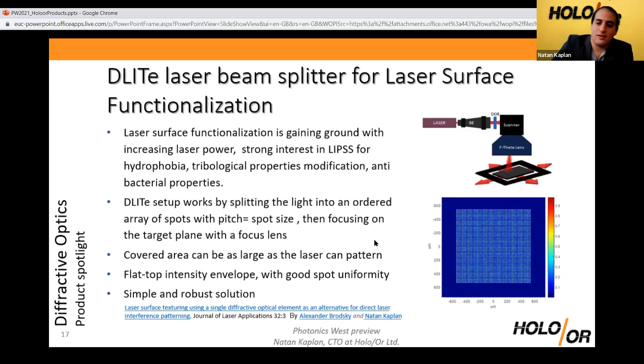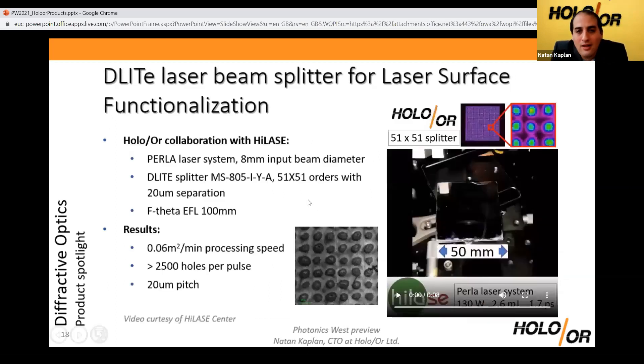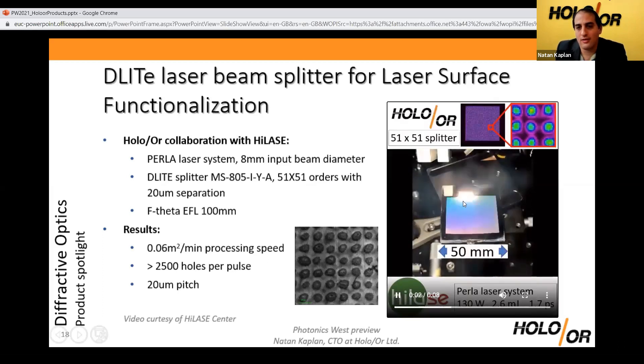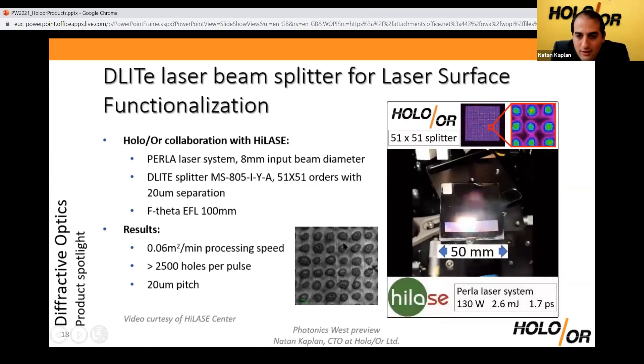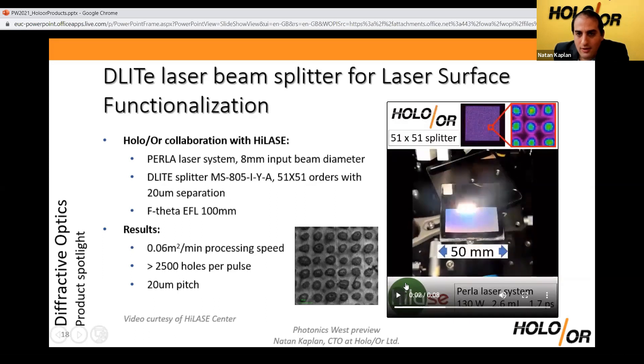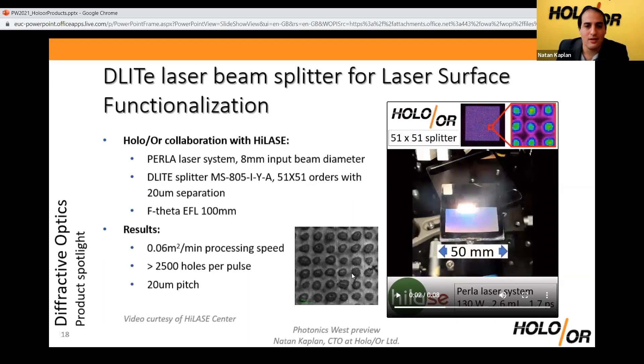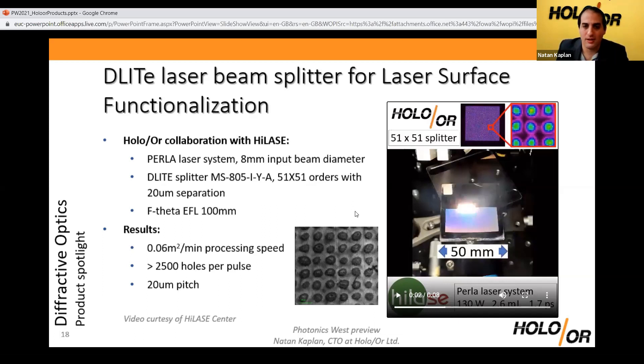To prove this concept, we did an experiment together with the HiLASE center of the Czech Republic using their PERLA laser system — an ultra-short laser at 130 watts. Our element was scanned over the area of a 4×4 centimeter sample. The square you see is the area being patterned simultaneously with 2,500 spots at 20 micron separations. Using different optical setups with the same DOE, you can achieve different densities or pixel types, such as elongated lines. Given enough laser power, you can reach commercial-scale throughput with a simple system of a single D-Lite element and a scan lens.